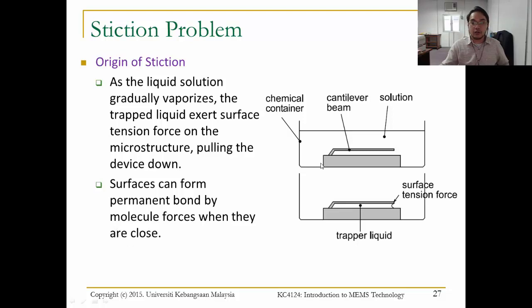For example, when you are etching away the sacrificial layer, you put it inside a solution etchant. When you take it out for the drying process, some of the etchant liquid is trapped inside, for example here, underneath the cantilever beam. This trapped etchant will dry out. At the same time, the surface tension will pull these two parts together and make them stick. And sometimes this sticking can be permanent.